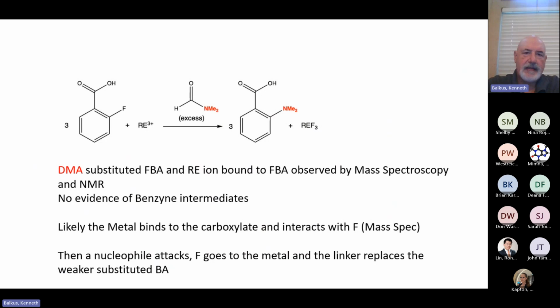And one of the reasons we do think that is because if we look at after just a reaction of 2-fluorobenzoic acid with a rare earth ion, and we look at the mass spec, we'll see species where it looks like dimethylamine now is bound to where the fluorine was. Okay. And by the way, we see no evidence of benzyne as an intermediate or free radicals, though it's tough to use free radical traps in the presence of rare earth ions because the rare earth ions usually react with the free radical traps. But at any rate, we think that the metal is also binding with the carboxylate. We see these kind of species in the mass spec, although that's tough to do too because we got to do this in DMF and they don't like DMF in the mass spec. But at any rate, that's a different story. So we think that the DMA, or at least in the case of DMF, is important for this reaction.